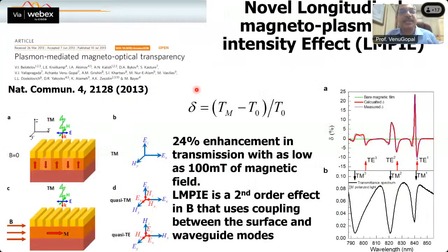And we also showed a novel longitudinal magnetoplasmonic intensity effect, where if you use this waveguide mode resonances, so if you take a little thicker layer, you can use this plasmon mode, strong local field to couple to this waveguide mode, and then it passes out, and during this interaction, you can have change in the polarization of your incident light.